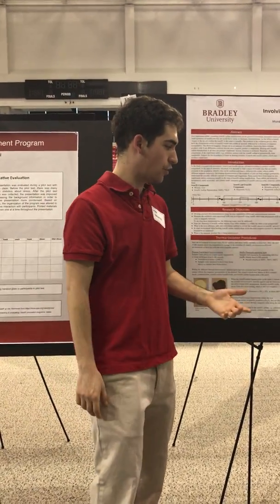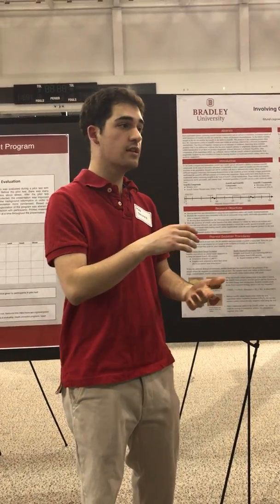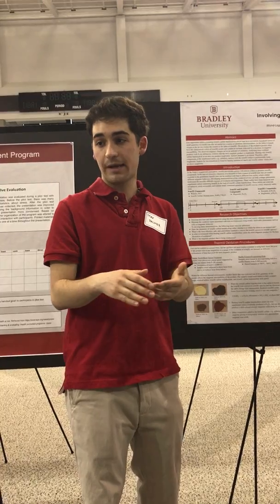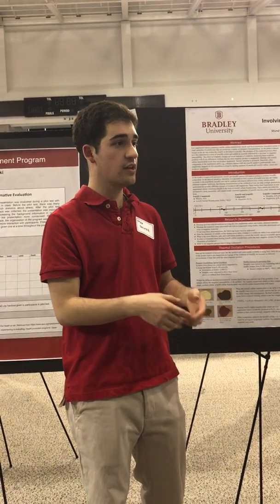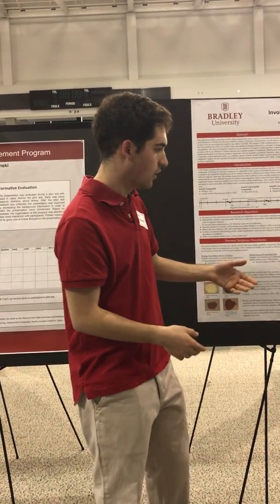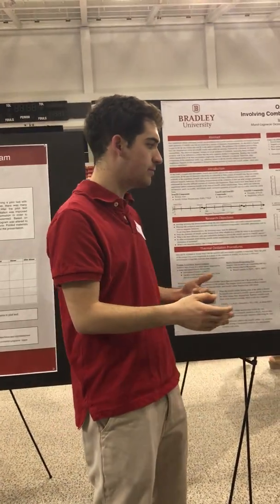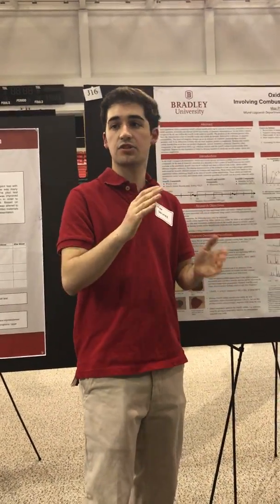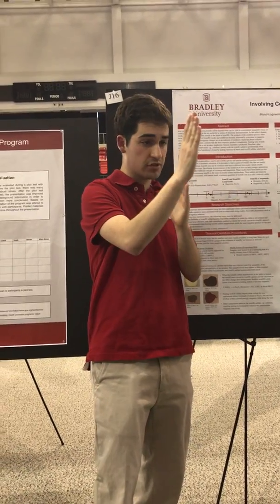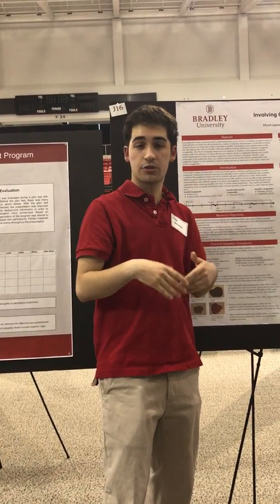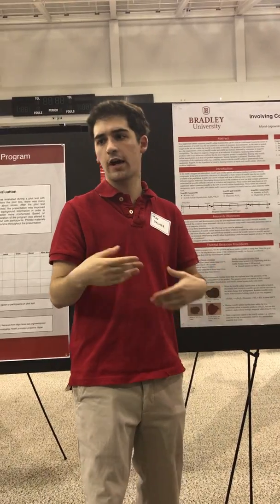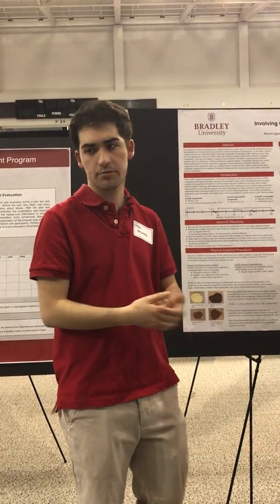The way to overcome that was we would spike all of our samples with an internal standard, which we used as silicon. And so we would know where our internal standard peaks are. Then between each trial, we would be able to line up those internal standard peaks, which would account for or overcome any possible human error or instrument error.